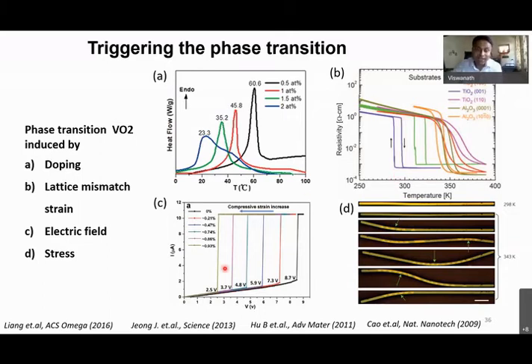Same way, electrically the phase transformation can be triggered, and more importantly, the threshold voltage for the insulating to metallic phase transformation can be manipulated. With strain, compressive strain can reduce the threshold voltage from 8.7 volt to 2.5 volt. There are also interesting works on nano beams and nano wires. When you just bend with the simple help of tweezers, we can induce the phase transformation. Again, it's a very interesting subject. It forms very periodic structures, with metallic domains nucleating in the insulating phase. Again, due to surface and strain energy minimization, these kinds of coexisting phases or phase evolution have already been demonstrated.